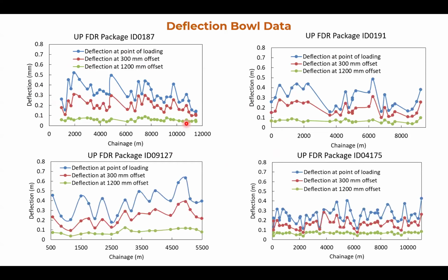Overall, what we can see is the deflection at the point of loading varies between 0.1 mm to around 0.6 mm. Sometimes, wherever there have been poor conditions or localized failure, the deflections can even go up to 1 mm. But overall, the deflection is around 0.5 mm. This data is pre-monsoon, before the monsoon season. We are also taking readings after the monsoon season. Right now, the evaluation is in progress, just to understand the correlation under wet conditions.